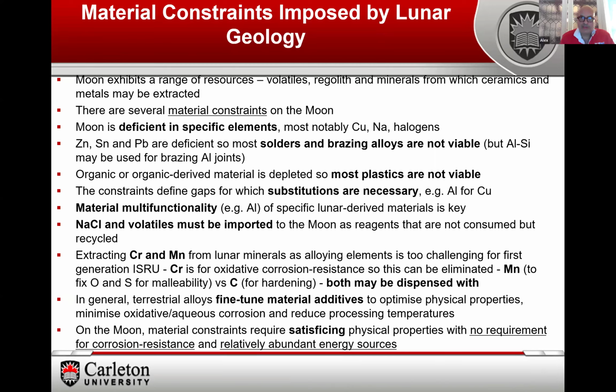So, for example, instead of copper, which we use as an electrical conductor, we can use aluminium, for example. And we can exploit material multifunctionality, which I'll show you in a few moments. For example, aluminium basically is a multifunctional material that can be adapted for many different applications. This will require some reagents to be brought from Earth because of the lack of halogens and sodium. So we're proposing that we bring salt with us to the moon, which we use as a source of reagents, but these are not consumed, these are actually recycled, and we'll see that in a few minutes.